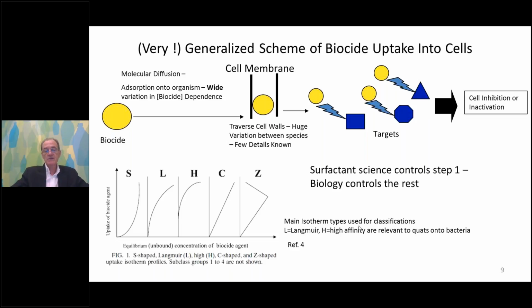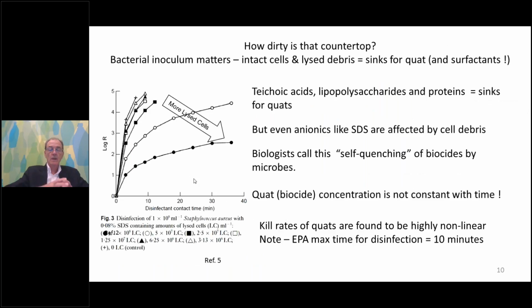And it turns out in many cases that those adsorption isotherms tend to be either Langmuirian or high affinity. And we'll see why. The number of bugs, the inoculum that we use in the testing of the efficacy of these products, matters. How many bugs are on that surface? It matters a lot because, as we just saw, both the intact bugs and the cells that are dead or debris are sinks for quat. Things like teichoic acids and proteins and lipopolysaccharides are great sinks for our quaternary ammonium compounds. But you know, you can even disinfect with good old SDS, sodium dodecyl sulfate.